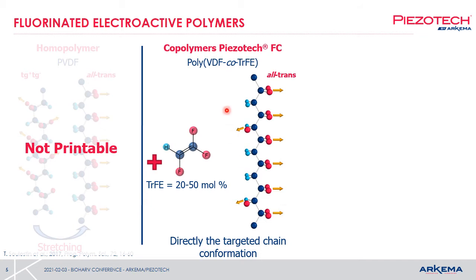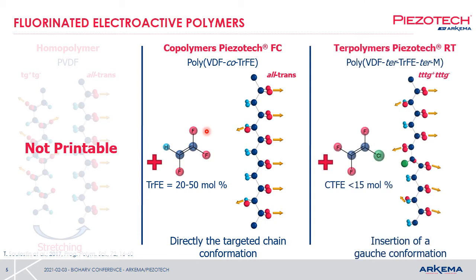In addition, these copolymers are much more soluble in a wide range of solvents compared to PVDF, especially non-toxic solvents. And almost 20 years later, beginning of the 21st century, a new range of products was discovered, the terpolymers. So the introduction of a specific third monomer, chlorotrifluoroethylene, or CTFE. If you introduce about 8-10% of this third monomer, you're going to disrupt a little bit the all-trans conformation and create Gauche conformation, create nano domains that are going to change a little bit the electroactive properties without losing everything.